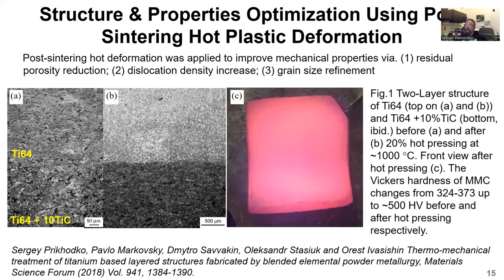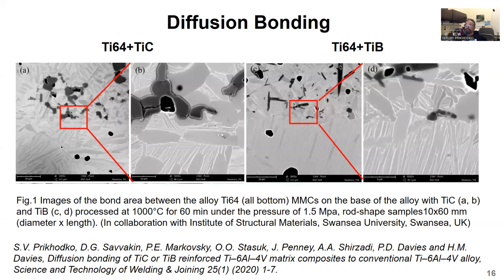I will not commit much time describing not very successful efforts on improving mechanical properties through hot rolling or pressing, which is considered one of the most common ways of fixing the porosity issue of powder metallurgy products. In general, hot pressing has some potential, but it is still very limited. We believe that optimization of each layer structure and then layer bonding using either diffusion bonding, friction welding, or hot isostatic pressing is a feasible way to approach this problem.